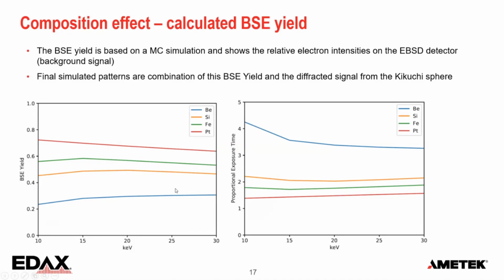When you drop the KV, the efficiency changes, and platinum is still nicely increasing the yield, but beryllium is dropping. So the lower the KV, the lower the signal. And again, that is a backscatter coefficient property. So that also goes for other types of materials that are very light. When we then invert this chart into the required exposure time, so these are just relative exposure times, of course, the lighter the material, the longer you have to wait. And at lower KVs, that effect is getting worse.